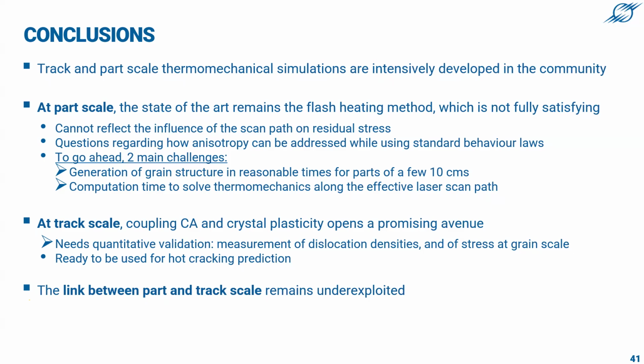So provided that you are able to characterize the behavior of your material under the shape of single crystals, and that's definitely possible to do, then you can really perform relevant track scale thermomechanics. So this obviously needs quantitative validation, and measurement of dislocation densities, measurement of stress at grain scale is really a challenge.